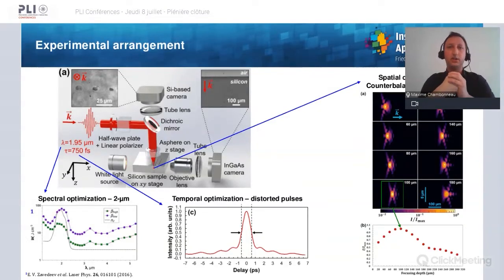As in the literature, it was recently reported that non-perfect Gaussian pulses are beneficial for achieving modifications inside the bulk of silicon. And a third optimization is illustrated here, which is a spatial optimization, which consists of counterbalancing the spherical aberrations which are provoked by the aspheric lens reported here, with the spherical aberrations which are induced by the interface between air and silicon. And by performing some very simple linear propagation simulations, we could see that around 100 or 120 microns, the intensity is theoretically enhanced in that case.